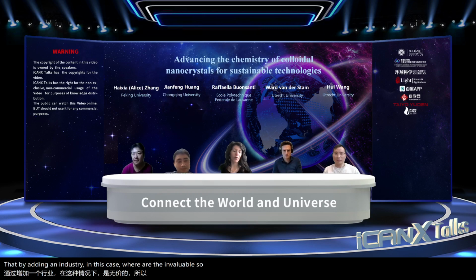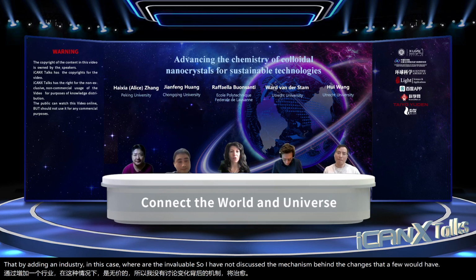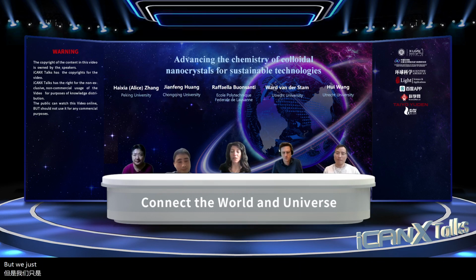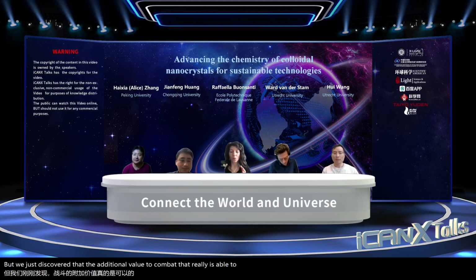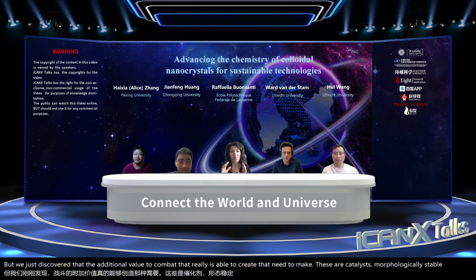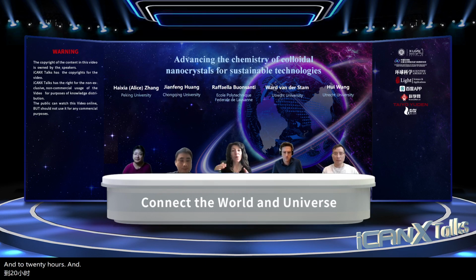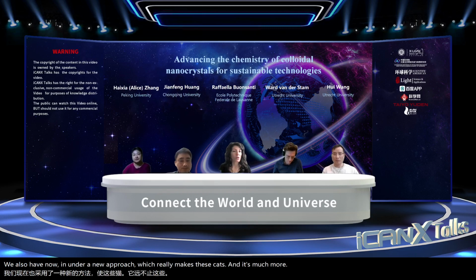So I have not discussed the mechanism behind the changes that occur eventually in this catalyst, but we just discovered that the addition of gallium to copper really is able to make these catalysts morphologically stable up to 20 hours. And we were limited by the flooding of the cell. We also have now another new approach, which really makes these catalysts much more stable.